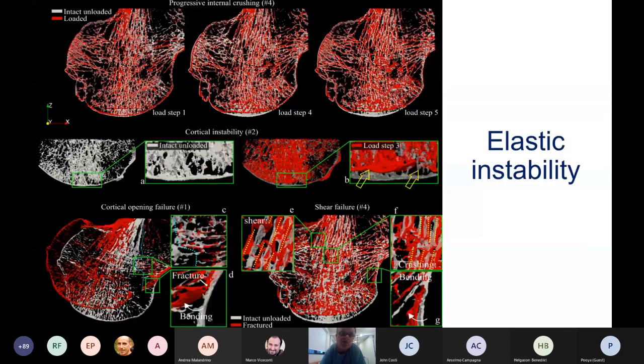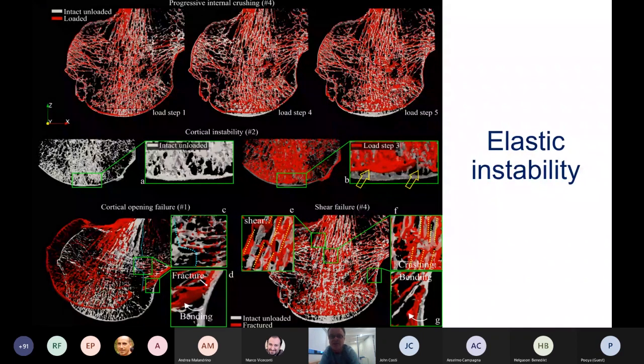So does elastic instability occur during this whole process? In the top row, we are seeing the comparison between the unloaded and the loaded at the very first step, an intermediate load step, step 4 in the middle, and the very last load step before fracture. In none of these conditions is there an evident elastic instability happening throughout the internal volume. If we look at the cortex, middle row, we see that elastic instability starts to be observable since a very initial load step in the region of high compression. On the very right of the middle row, we are seeing two regions indicated with the yellow arrow where we have a local deformation due to instability.